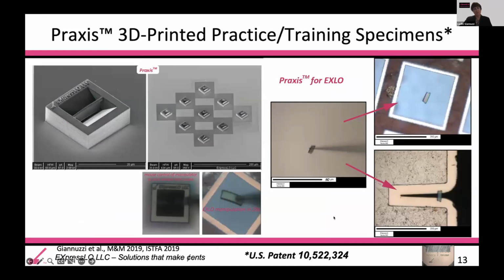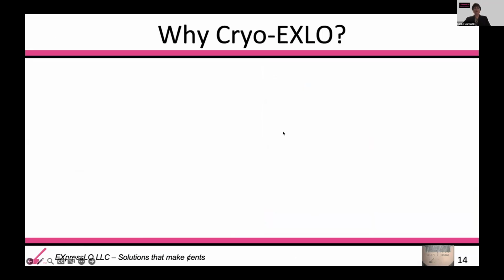The one other thing that we have also developed are these practice 3D printed specimens, which are called praxis. Praxis is actually Latin for practice. These specimens allow us to teach and train users not only how to do ex situ lift out as shown here on the right, but theoretically you can also teach people to do in situ lift out as well. In fact, it was these specimens that we used to first qualify and show that cryo ex situ lift out was possible.